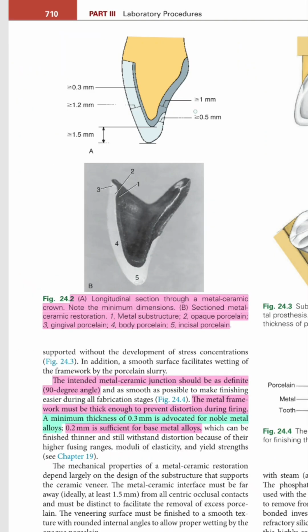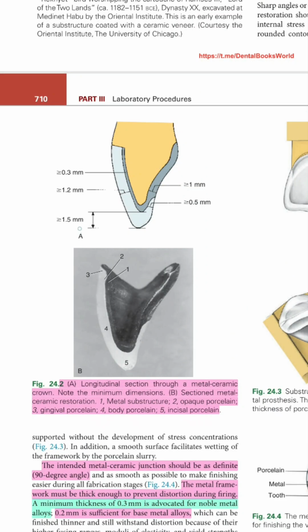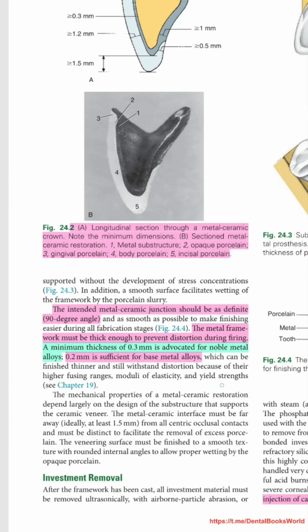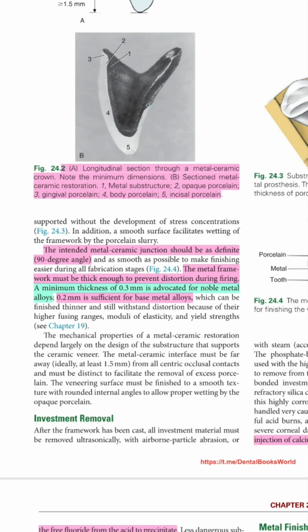Here we can see the variation of the thickness that should be maintained for the ceramic and the metal. A metal thickness of 1 millimeter is sufficient on the palatal surface, and 1.5 millimeters is recommended for the incisal porcelain edge. 0.3 millimeter is sufficient for the metal on the labial surface, and 1.2 millimeters is recommended for the porcelain thickness on the labial surface. The junction between the two materials must be as close to 90 degrees as possible, and its place must be